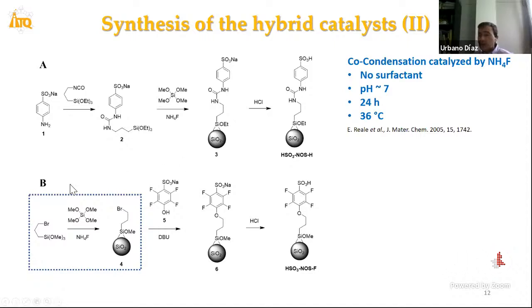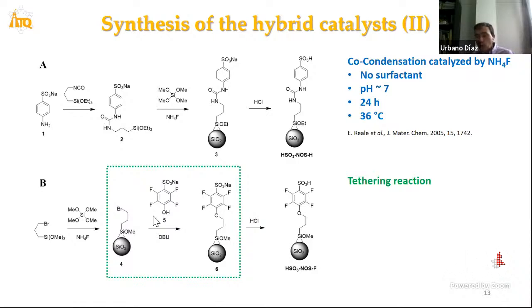Another strategy is the preparation of the mesoporous materials using bromide siloxane groups, using the same synthesis methodology based on the use of fluoride ions as a mineralizing agent in the presence of another silicon source, such as TEOS in this case, to obtain non-ordered hybrid mesoporous material with bromide pending groups suitable to perform a consecutive tethering reaction with sodium tetrafluorohydroxybenzenesulfonate molecules, to obtain finally this type of sulfonate groups linked to aromatic rings doped with fluoride ions close to the sulfonate groups.